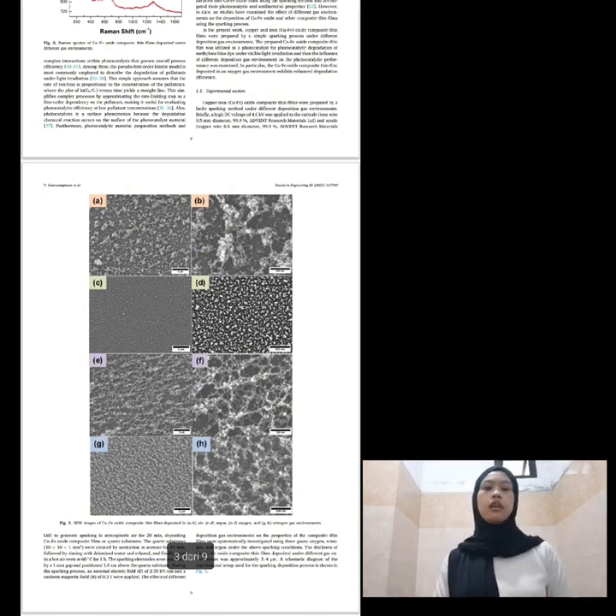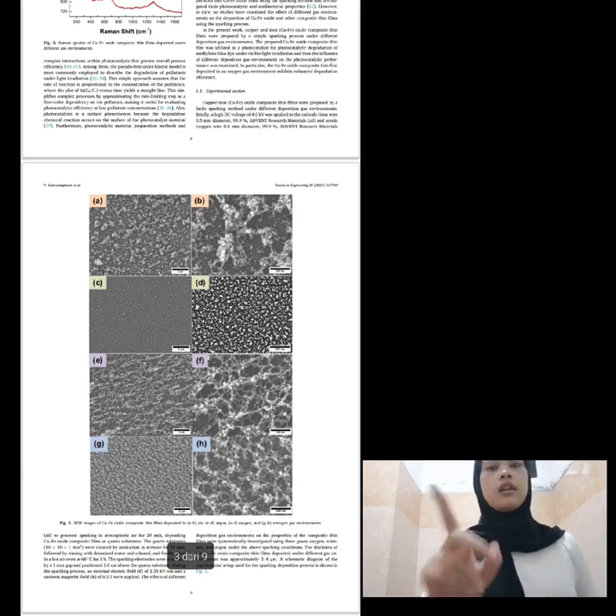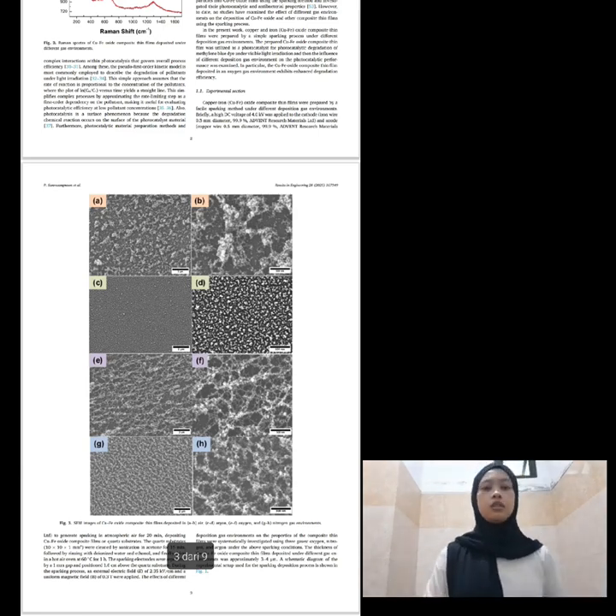Procedure: CuFe wires were used as electrodes with a high DC voltage to produce sparks. The process was done under different gases, O2 and air, for 20 minutes, depositing CuFe oxide thin film on quartz substrate. Electric and magnetic fields were applied to control particle formation and film structure. The film's thickness was about 3 to 4 μm.